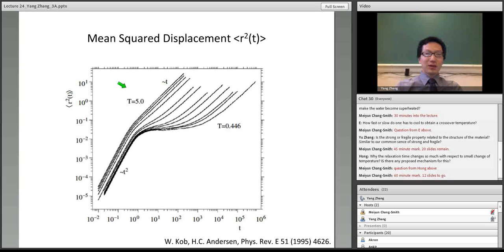And you can also see that in order to quantify the dynamic heterogeneity, there are many properties that have been proposed, but you can actually already see it from the mean square displacement, which can also be determined by neutron scattering experiment. The mean square displacement as a function of time. At very long time, all the particles diffuse, so the mean square displacement follows the Einstein diffusion law. At very small time, the particle is basically just rattling in the cage surrounded by its neighbors. As the temperature is lowered, there's this intermediate time range, an intermediate length scale feature, that corresponds to this dynamic heterogeneity.